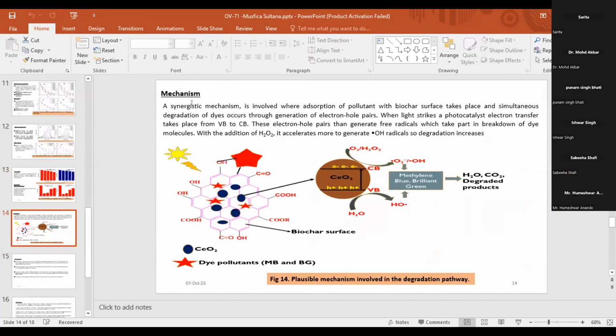In the mechanism, a synergistic mechanism is involved where adsorption of pollutants on the biochar surface takes place and simultaneous degradation of dyes occurs through generation of electron-hole pairs. When light strikes a photocatalyst, electrons transfer from the valence band to the conduction band. These electron-hole pairs then generate free radicals.